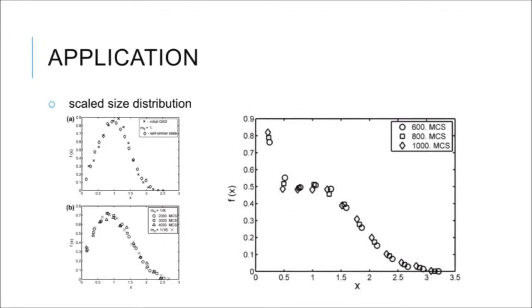We see, again, self-similarity, but the distribution now shows a huge amount of relatively small grains, and the distribution becomes much broader again. So now we have grains that are more than 3 times the average size. And like I said, we have this very particular behavior with this peak at very small grain sizes.